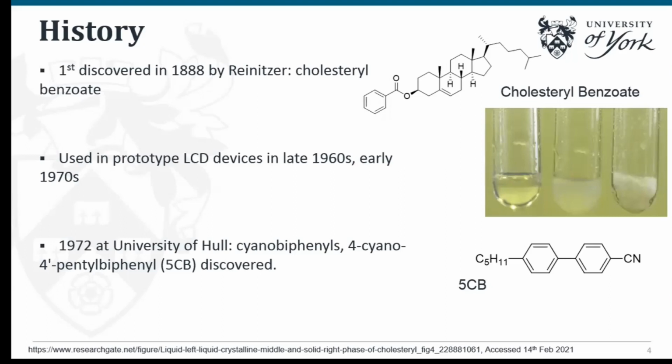Initially, they were only of academic interest, but in the late 1960s, early 1970s, they were used in prototype liquid crystal display devices, and particularly after 1972, when at the University of Hull, the cyanobiphenyl group of liquid crystals, with the most famous being 4-cyano-4'-pentylbiphenyl, affectionately known as 5CB, was discovered, which is a room temperature liquid crystal, which meant that liquid crystal displays no longer had to operate at temperatures above 100 degrees.